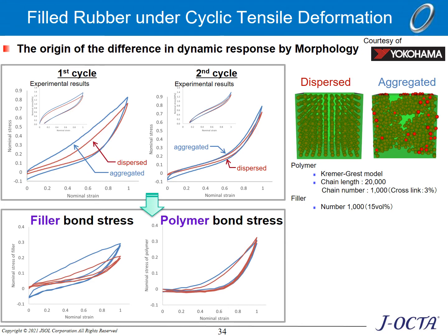What is interesting is the second cycle, where we can see from the graph, there is no hysteresis in the second cycle. This is the same for the aggregate and dispersion structures, and the experimental results show the same trend. Due to the large number of fillers, the system size is several hundred nanometers. For this reason, a supercomputer was used to perform the calculations. In addition, a slow deformation rate has been applied, which is slow enough to describe the rubbery state of the polymer.